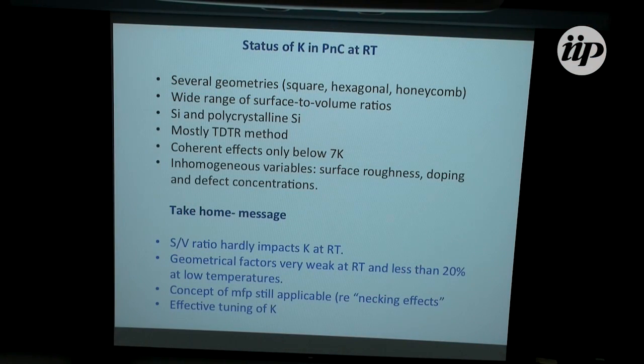There's also an agreement that the inhomogeneous parameters include surface roughness, which is quite serious when talking about making nanostructures. It includes doping, whether intentional or unintentional, unintentional being residual doping, isotopes, etc., and defect concentrations, which is not only how many you have per unit volume or area, but also how homogeneously they are distributed, right? So these were the kind of experiments done, and I showed you where the status was. There is pretty much an issue concerning most of these points.